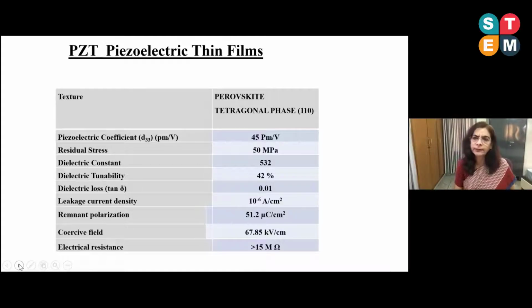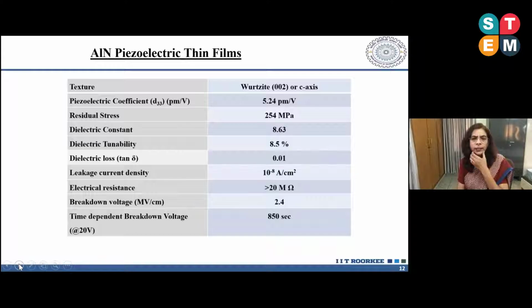We are also doing work on aluminum nitride piezo thin films, which show a piezo coefficient of 5.24 picometer per volt, resistance greater than 20 mega ohm, leakage current density of 10 to the power minus 8 ampere per centimeter square, and all the other parameters.